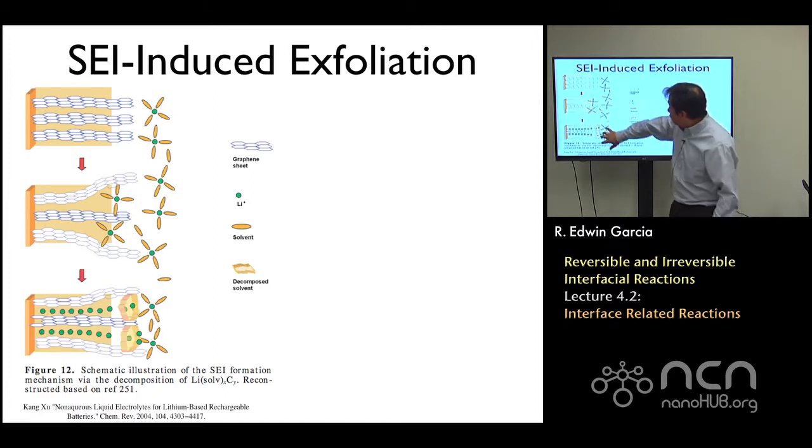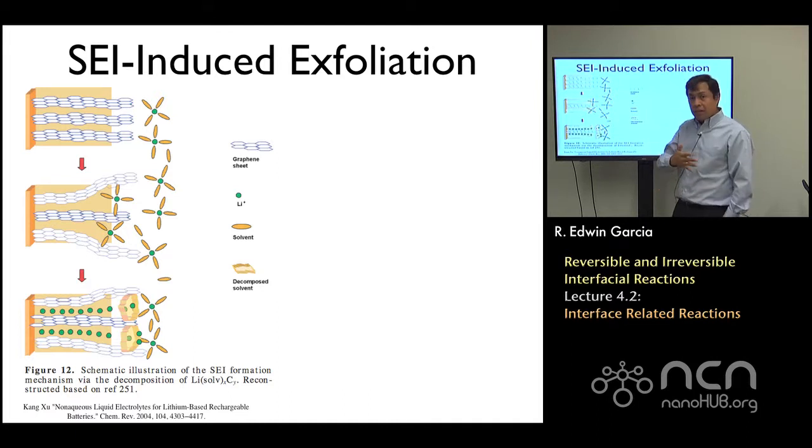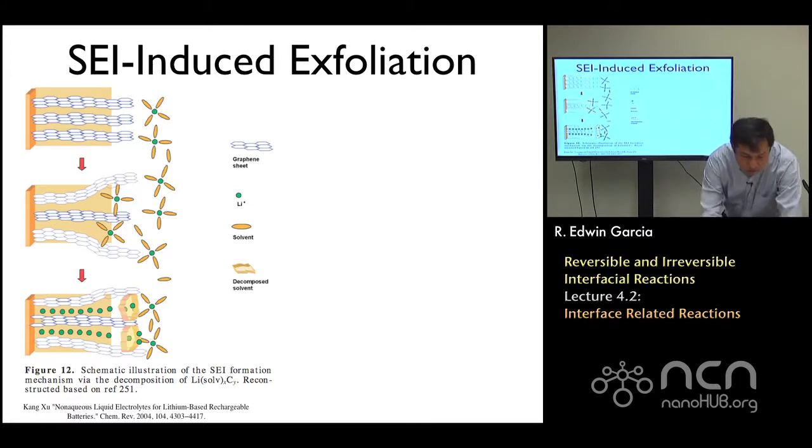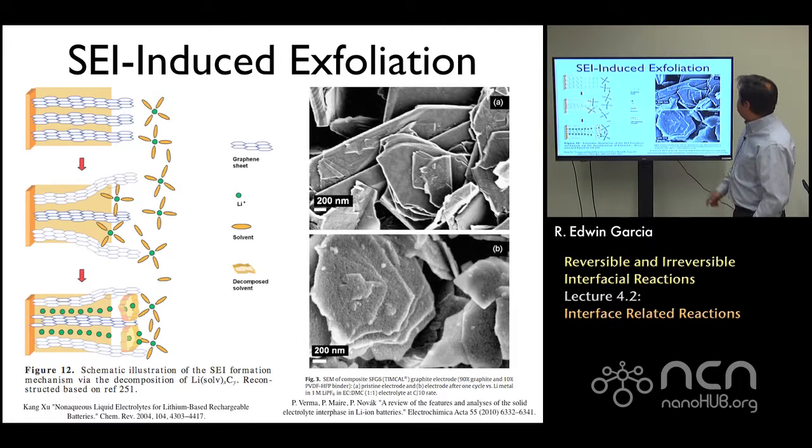As a result, you can see these surface layers of graphite exfoliating into the electrolyte, losing some capacity and impacting the overall response of the system. You can see here in these micrographs how the material looks very nice and pristine before being used, and after, sometimes you can see how all these blisters have formed and how the material is losing charge as it's all redissolving in the electrolyte.